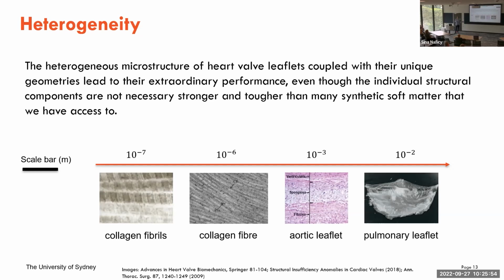The part which is rich in collagen fiber, as I mentioned, has the collagen fibers oriented in the circumferential direction. So we have heterogeneity in terms of composition, and we also have anisotropic properties because of the alignment of already anisotropic collagen fibers. This whole thing leads to a tissue which is highly anisotropic.